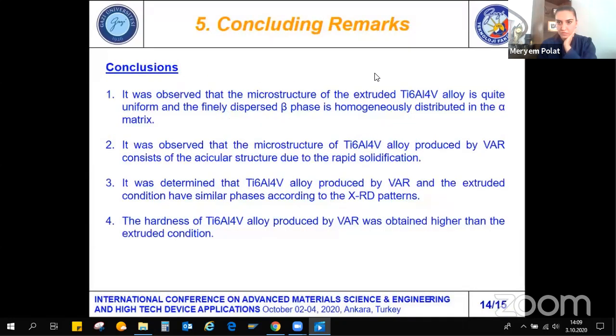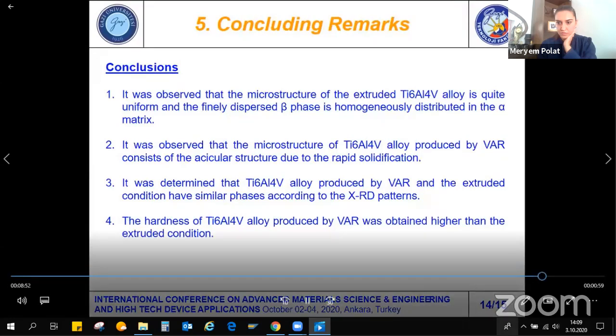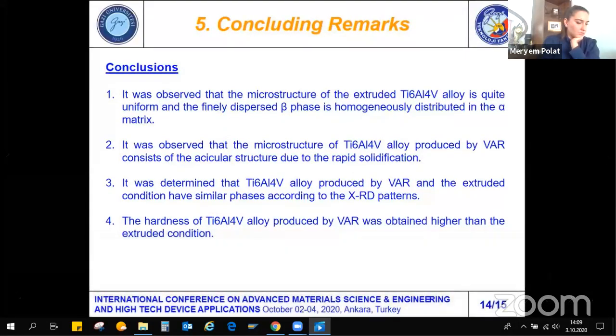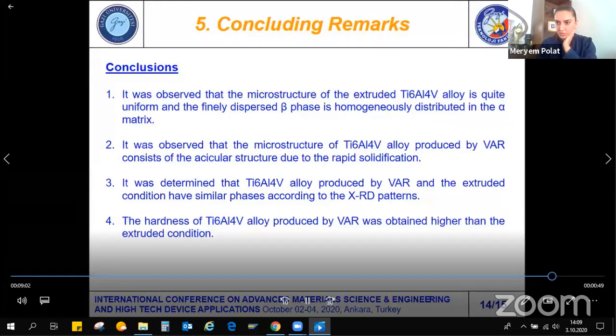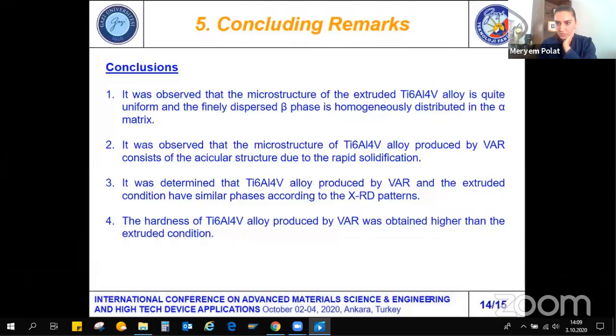Finally, conclusion. It was observed that the microstructure of the extruded titanium 6 aluminum 4 vanadium alloy is quite uniform, and finely dispersed beta phase is homogeneously distributed in the alpha matrix. It was observed that the microstructure of titanium 6 aluminum 4 vanadium alloy produced by vacuum arc remelting consists of the acicular structure due to the rapid solidification.